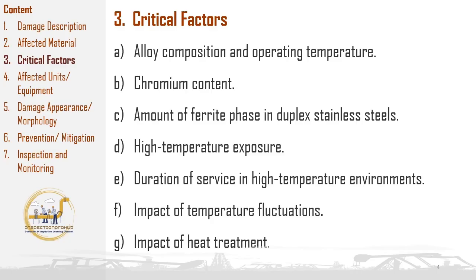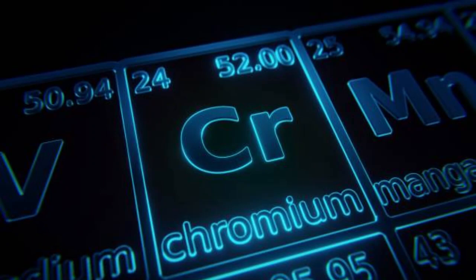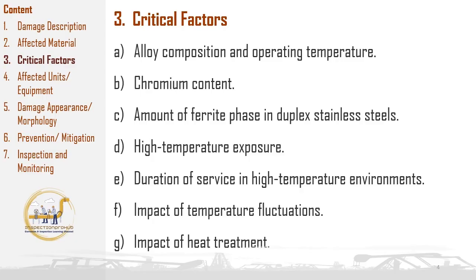Second critical factor is chromium content. Chromium content plays a critical role in the susceptibility of stainless steels to embrittlement. Alloys with lower chromium content, such as 405, 409, 410, and 410S, exhibit a reduced tendency for embrittlement compared to higher chromium materials like 430, which contain 16 to 18% of chromium, and 446, which contain 23 to 27% of chromium, and duplex stainless steels, which contain 22 to 25% of chromium, which are more vulnerable to this phenomenon.